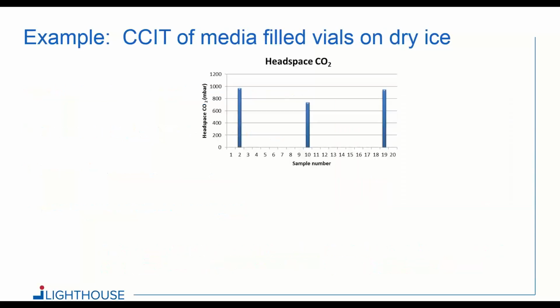So of course, you could directly measure any CO2. Again, on dry ice, you could look for CO2. What we often do in development studies is also use -80 freezers that have an open box of dry ice in the freezer. The freezer itself becomes a CO2-rich environment. So then the CO2 gas you can see as a tracer gas, looking for any vials that are losing closure. So clearly here, 3 out of the 20 media-filled samples leaked during the storage on dry ice, and have very high levels of CO2 inside.